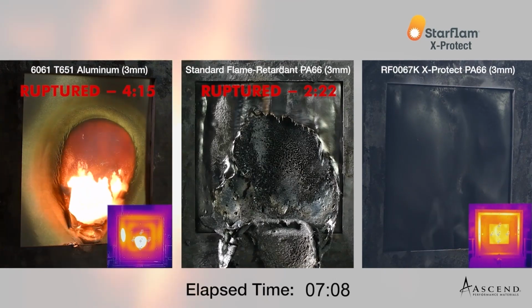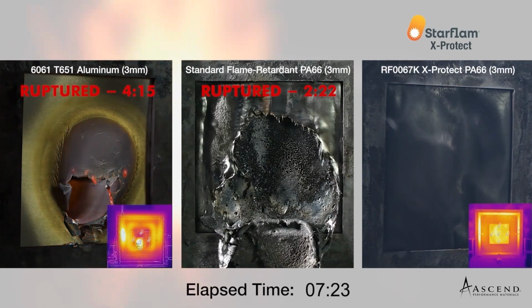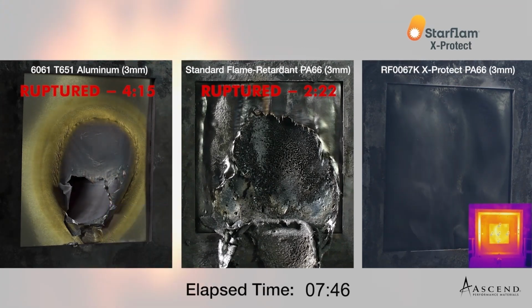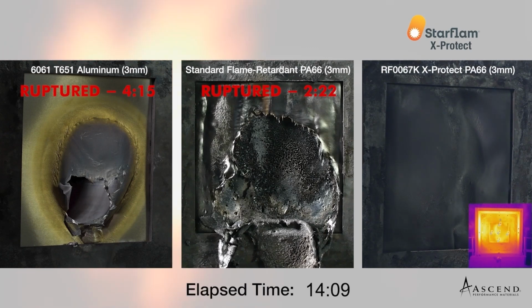And on the right-hand side, we're looking at Starflam X Protect, that after that initial buckling really doesn't change anymore. So the flame keeps burning, as you see in that IR picture, and the plaque withstands this exposure throughout 15 minutes, which is this timestamp where the lab decides that they would prefer to shut down the burner for their safety protocol. So based on this test, and this is the power plant fire penetration test, Starflam X Protect can be rated fireproof.